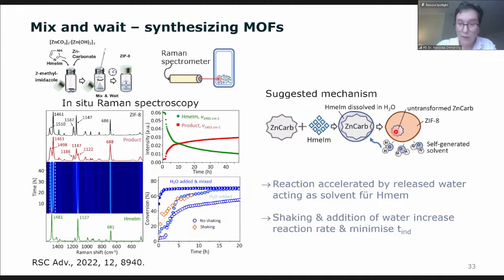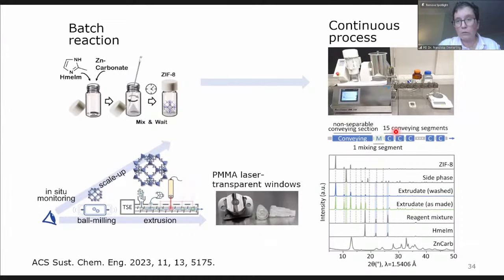And then we wanted to see whether we can use this exact reaction for upscaling. And that's the basic idea. So we want to go from the vessel system to a continuous process. And we use here our extruder to monitor the process. We needed some PMMA windows to shine our laser through. And you can see here first data. So it works quite nicely. We have the extrudate directly, and then after washing, it looks already like the commercial ZIF-8.